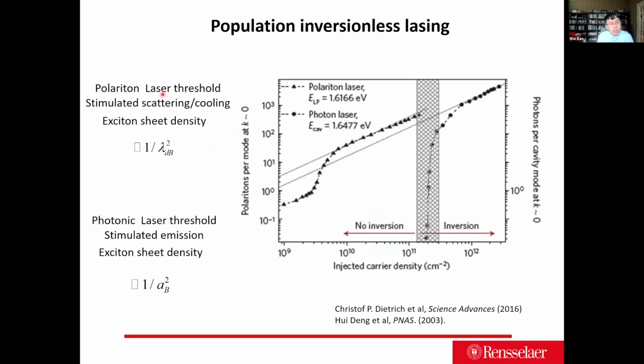So essentially, at the polariton laser threshold, once you go into the massively occupied BEC states, you rely on the stimulated scattering or cooling mechanism, which is related to the exciton sheet density and the de Broglie wavelength of the quasiparticle. While in the photonic laser, you have stimulated emission, which is related to the Bohr radius of the exciton density. So essentially, the polariton laser will have a much lower threshold compared with the same structure as a photon laser, as demonstrated by the researchers.